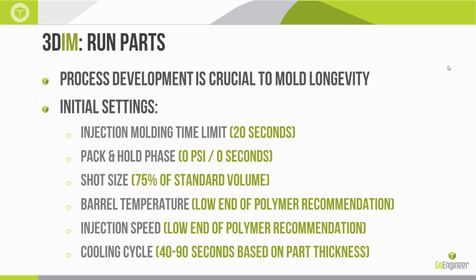So what they recommend is an injection mold time limit of 20 seconds. You don't want to have that nozzle up against the mold for longer than 20 seconds, injecting material. You're going to do a pack and hold phase of 0 pressure, 0 time. So you're not going to pack and hold this. A shot size, you're actually going to undershoot it to start with, 75% initial setting. A barrel temperature, you're going to want to set at the low end of whatever plastic you're using recommends, and also an injection speed at the low end, and then a cooling cycle for the part from 40 to 90 seconds.